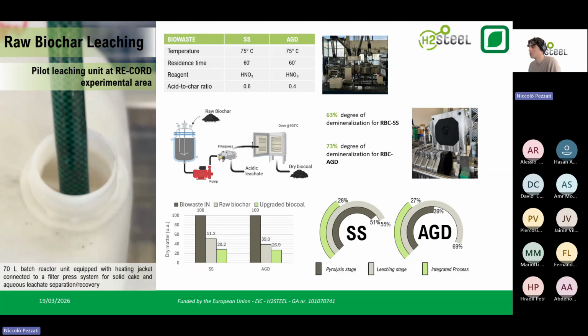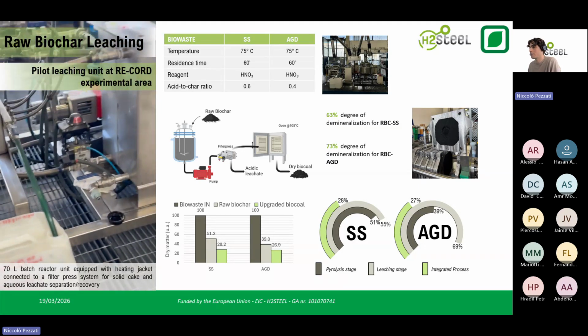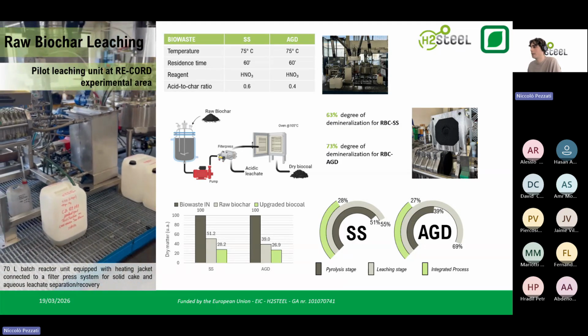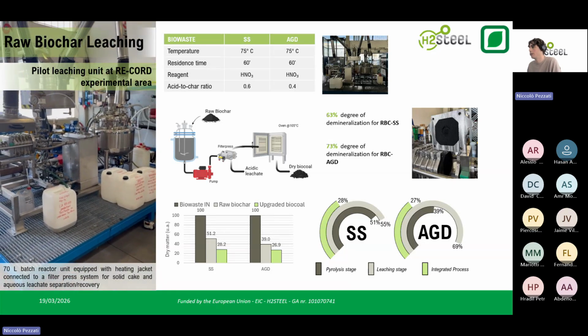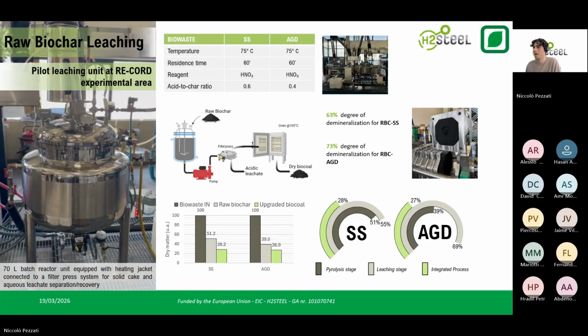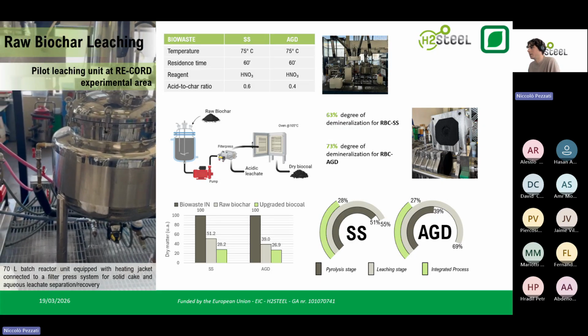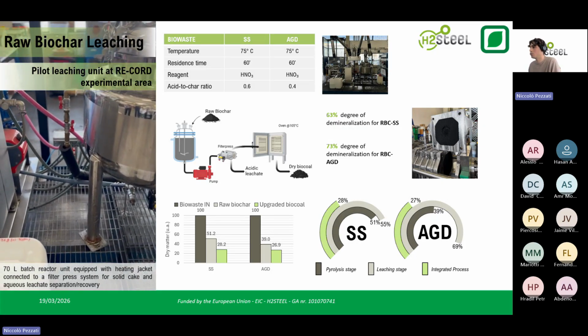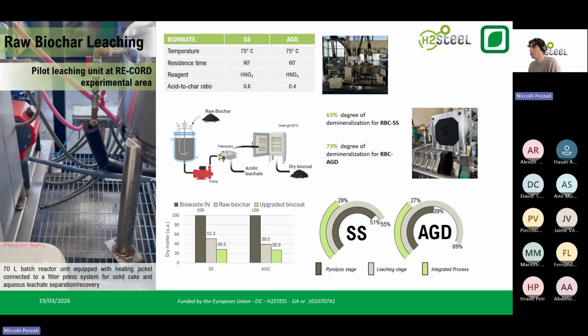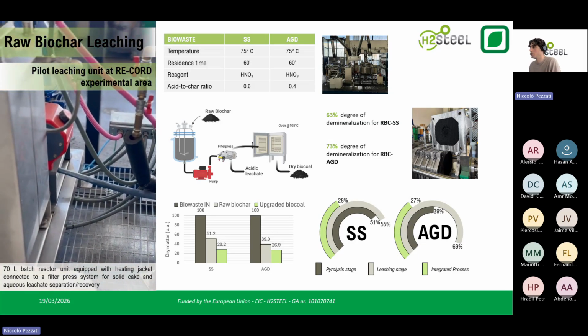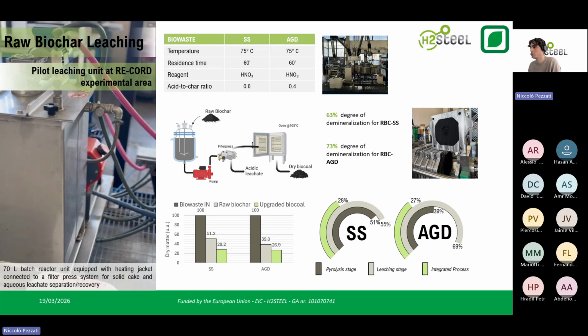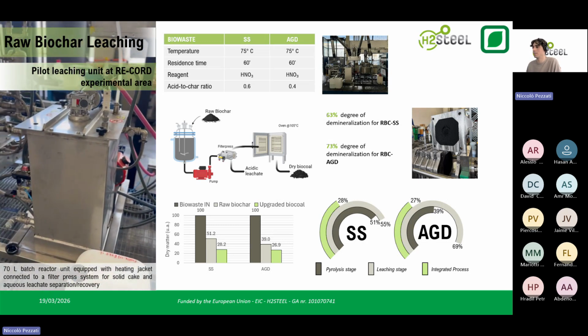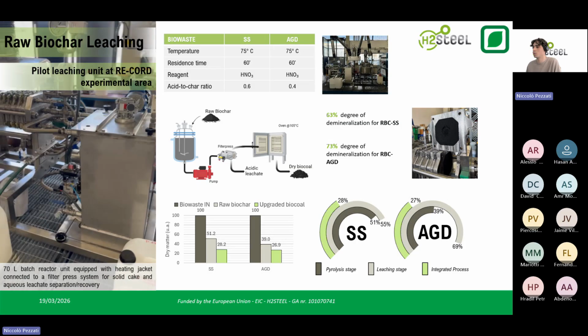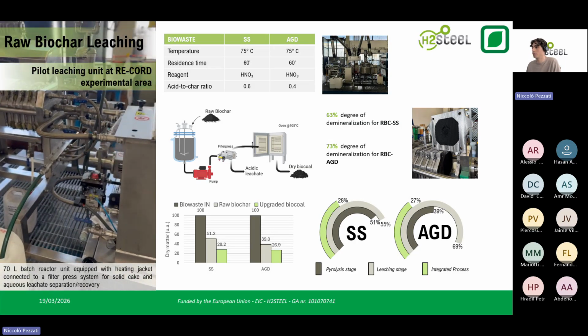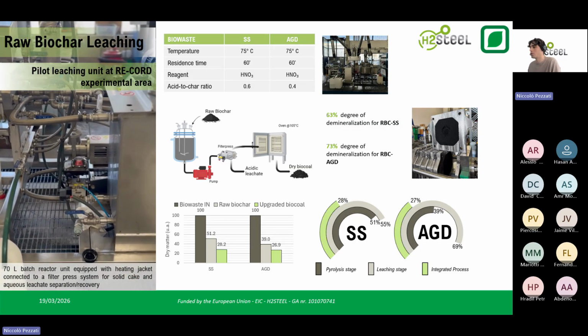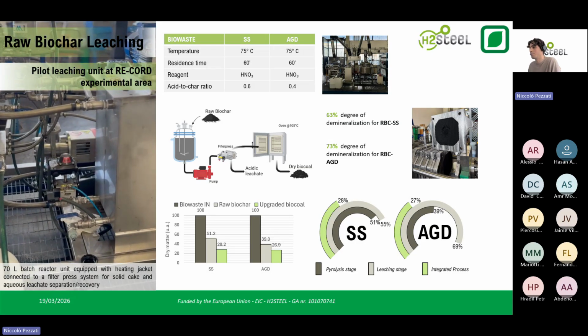And the treatment, as I was saying, allows to extract the inorganic elements from the solid into an aqueous phase. And as I'm reporting here, it is possible to achieve a 63% degree of demineralization when treating the raw biochar from the sewage sludge, whereas this value is even higher, equal to 73% when treating the raw biochar from the agricultural digestate.